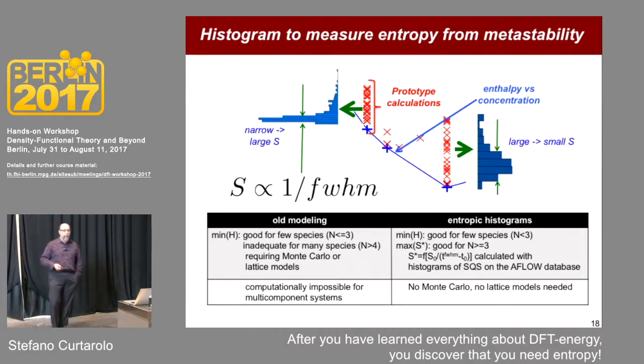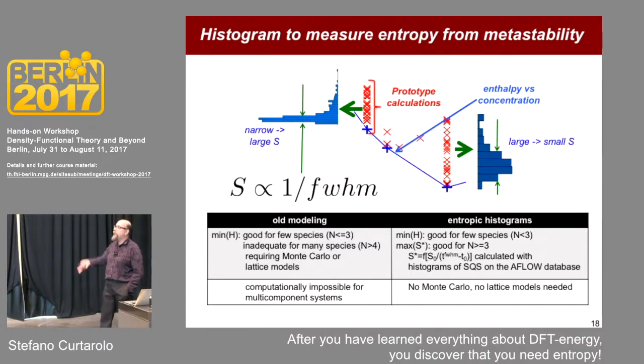Entropy, remember, if you're able to calculate all the possible states, is really the thermodynamic density of states. Here you study electronic density of states, right? The number of states within a delta of energy. If you do phonons, you can calculate the phonon density of states. If you do magnetic excitation, the magnetic density of states. So you have E DOS, P DOS, M DOS. This is the T DOS. This is the thermodynamic density of states, the number of states of configuration within a delta of energy.